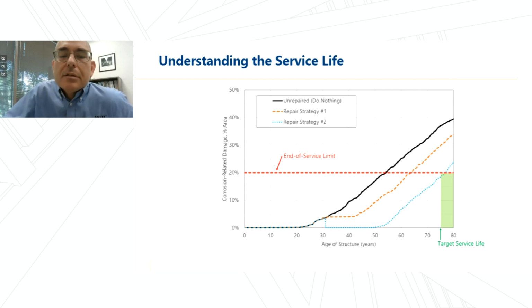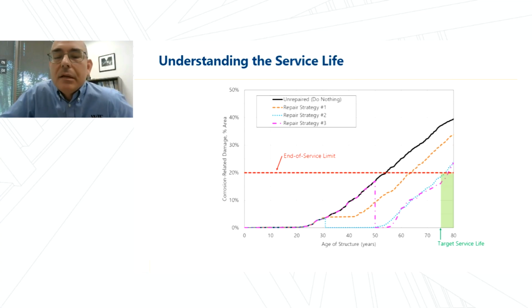So let's consider a third case where the owner is unable to install repair strategy number 2 at 30 years and needs to defer those repairs for 2 decades to the 50-year mark. And repair strategy number 3 in the pink line is shown at the 50-year mark. And you can see this repair strategy also meets the target service life, but the height of the vertical portion of the repair strategy 3 curve at 50 years is considerably higher than that of repair strategy 2 at 30 years. And the height of that curve is proportional to the effort needed to perform the repairs. So the cost and invasiveness of the repairs are considerably higher at the 50-year period.